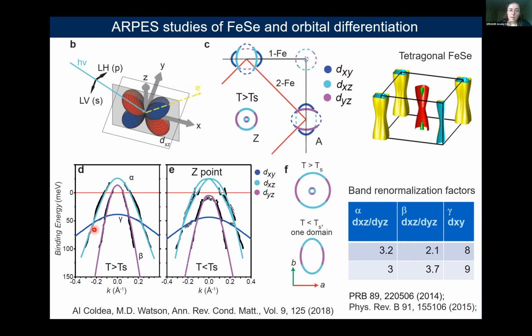Whereas for the other hole band, which was supposed to cross the Fermi level in calculation, is pushed about 50 milli-electron volts below the Fermi level. And this is due to the very strong band renormalization effects of about factor 8 or 9, which makes this system quite unique when we think about orbital differentiations and what role they play.